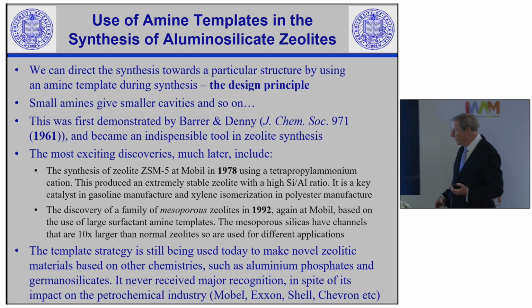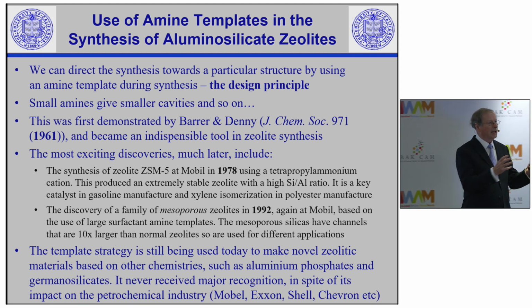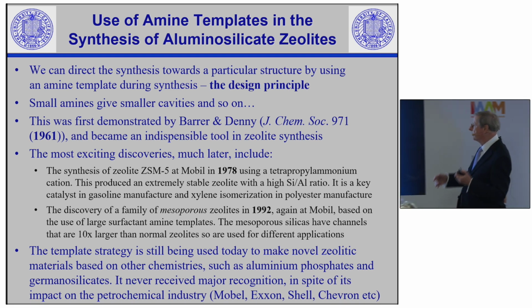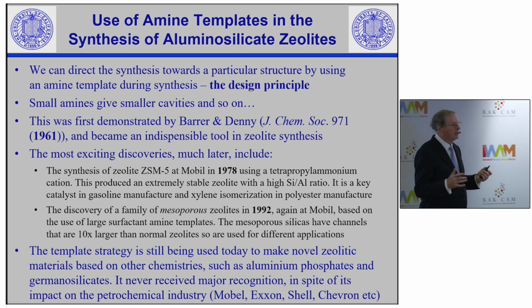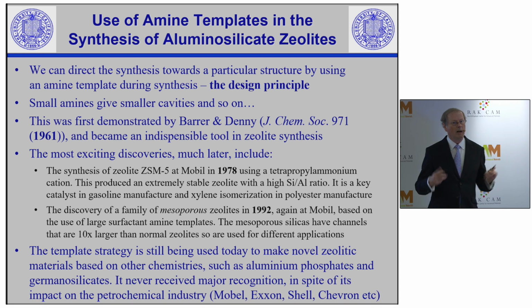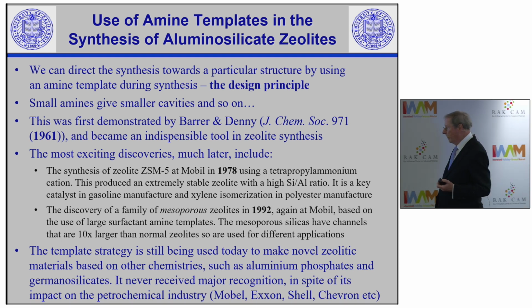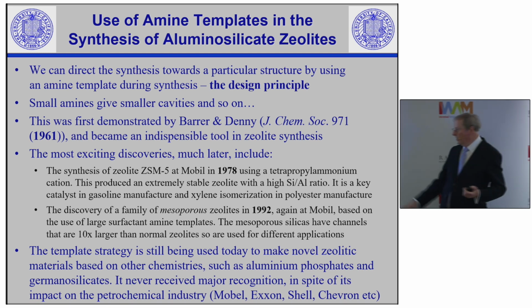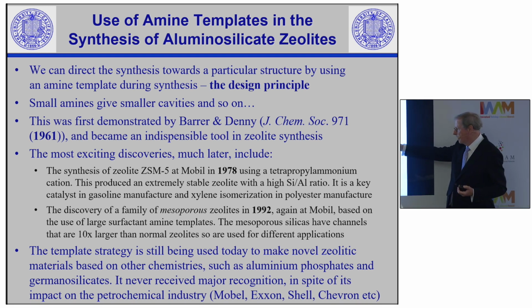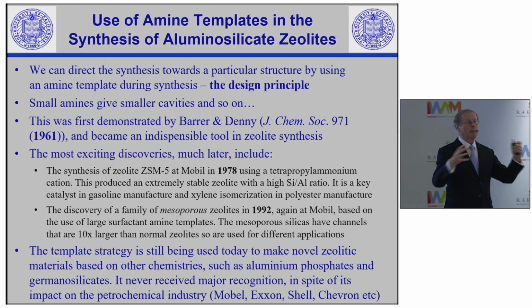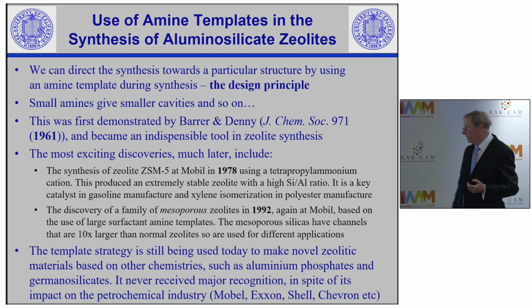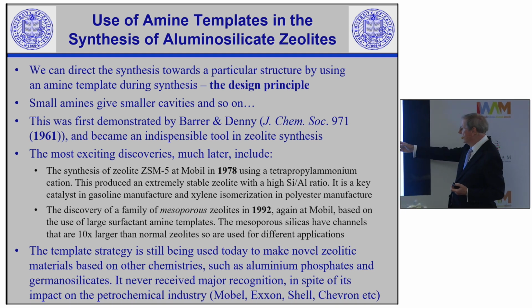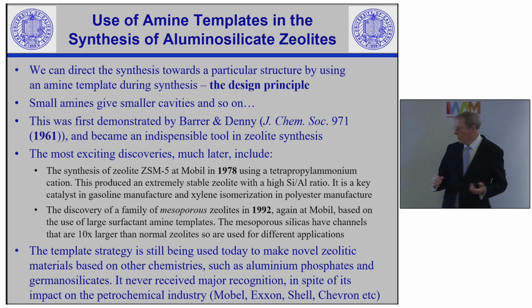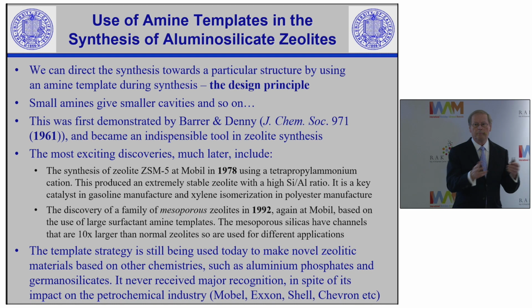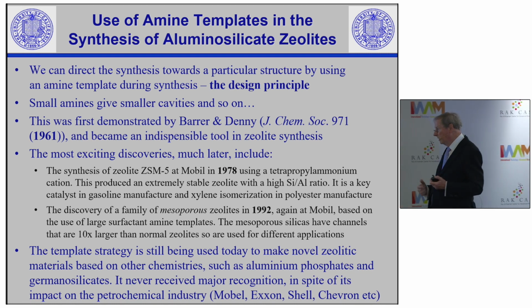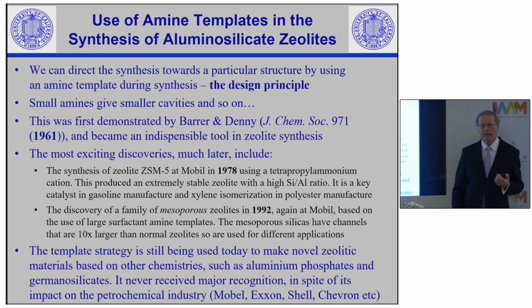And then people have extended it. This is sufficiently important in the oil and gas world that companies like Exxon and Mobil and BP, etc., would have research teams that worked on making different zeolite architectures and different catalysts. And I think the two most exciting discoveries, to my mind, one was a group at Mobil who used tetrapropylammonium, which is quite a large cation, so it makes a big cavity. And then you can burn it out afterwards to create the catalyst. That turned out to be a key material for two applications. One is xylene isomerization for making paraxylene, which goes into polyesters. And the other is as an important component of cracking catalysts for gasoline manufacture.